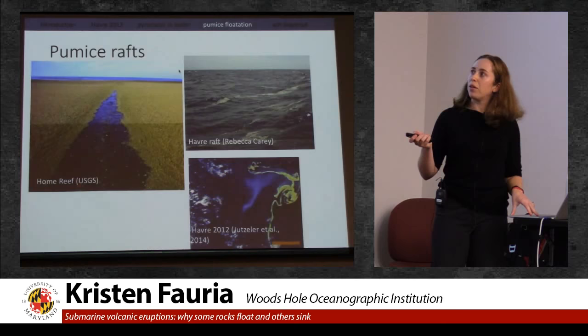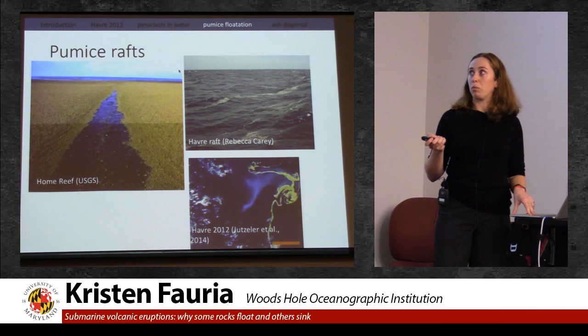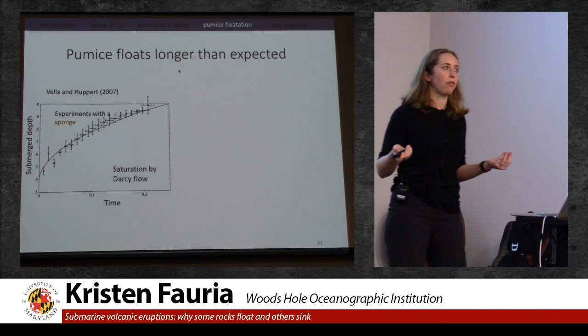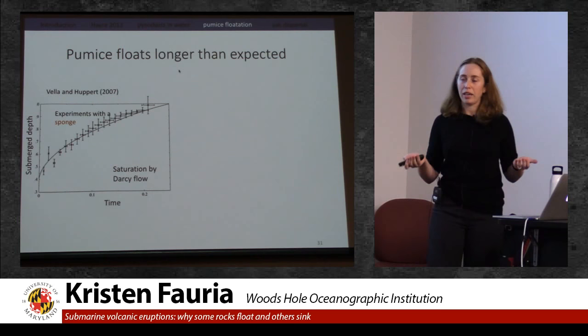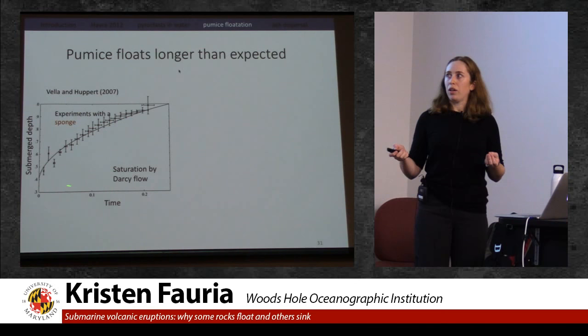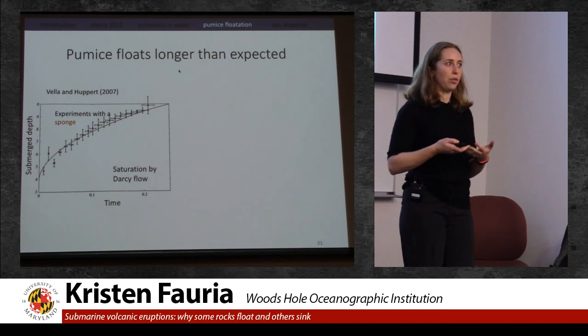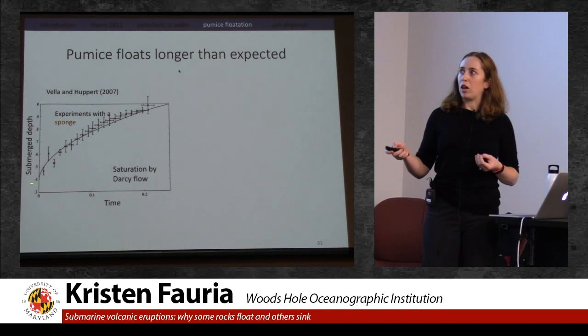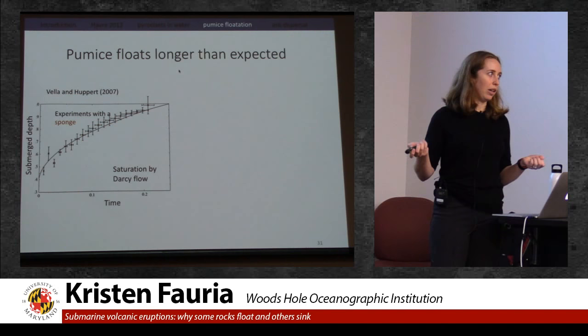So the pumice is able to float and potentially stay floating for a long time if it doesn't break down due to this abrasive process. But the ability for pumice to float for a long time is actually pretty unexpected because the pores of pumice are highly connected and water wets volcanic glass. If you model the saturation of a porous clast like pumice due to Darcy flow, where pressure gradients drive flow in, you find that your model can actually match observations pretty well for some porous material like a sponge.